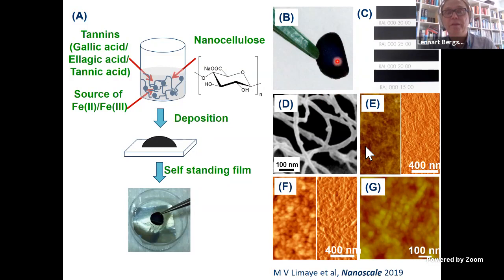As you can see, we can form completely black films, showing that there is a strong interaction between these coordination complexes and the cellulose nanofibrils.